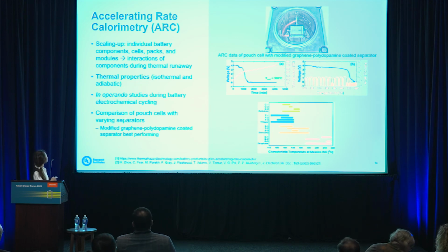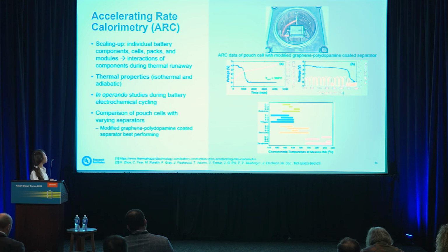Over here, the data is from this study on comparing pouch cells with varying separators. On the right, this is an example of the ARC data obtained for the modified graphene polydopamine coated separator. The authors concluded that with the graphene doping, the decomposition temperature of the cell is much higher compared to the standard electrolyte, Celgard trilayer, and standard separator, just because it's the best performing one.